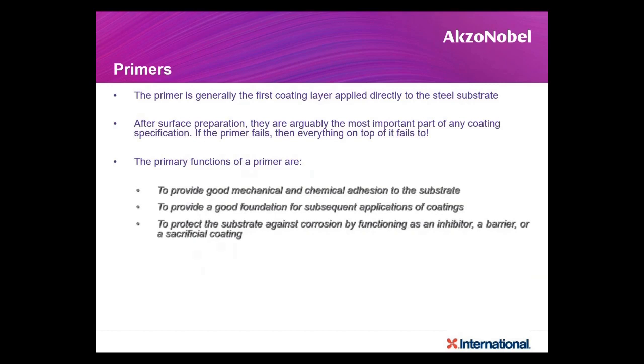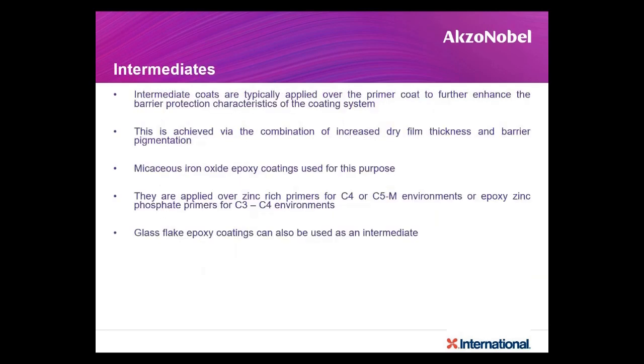Primers are generally the first layer applied onto steel. They give you good adhesion and good primary surface protection against corrosion. Keep in mind, a primer can be inhibitive, it can be a barrier, or it could be a sacrificial coating. Intermediate coatings are generally applied above primers in order to build thickness. Typically these intermediate coats have high thickness building capability, and many of them have a pigment called micaceous iron oxide, which helps in forming barrier protection. In some of the coatings, glass flake is also added to provide barrier protection.